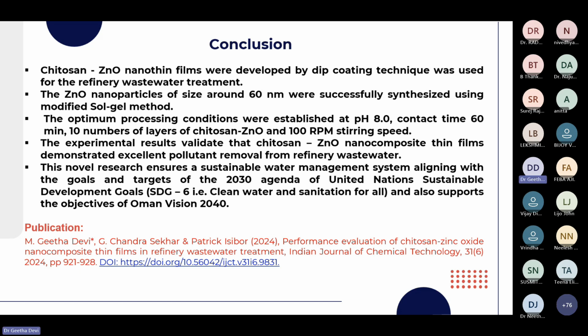Okay, in conclusion, these chitosan zinc oxide nano thin films were developed by the dip coating method, and used for the refinery wastewater, and also zinc oxide nanoparticles of size 60 nanometer were successfully synthesized using a modified sol-gel method. Our optimum processing conditions were obtained at pH of 8, contact time of 60 minutes, and 10 layers of chitosan zinc oxide with a stirring speed of 100 rpm.